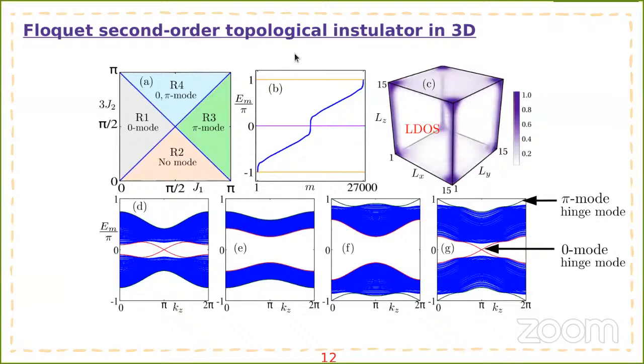Now to get the second order, we set alpha not equal to 0 and beta equal to 0, and in the phase 4 here also we can get the hinge mode. And to get the hinge mode, here it is plotted in the rod geometry. By rod geometry I mean the system has open boundary condition in 2 directions, whereas a periodic boundary condition in the z direction, and you can see the dispersive hinge modes in 0 and pi. And if we go to the real space system and plot the local density of states, you can see that the hinge modes are populated around the hinges of the system, and this feature is qualitatively the same for both 0 and pi modes.